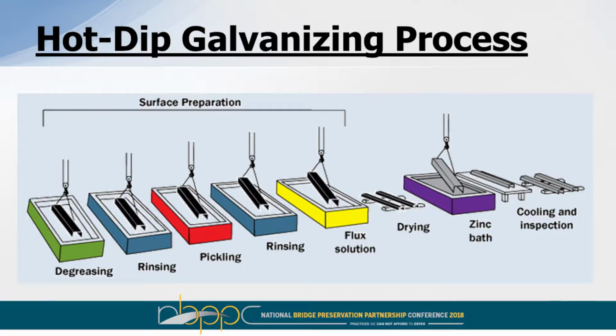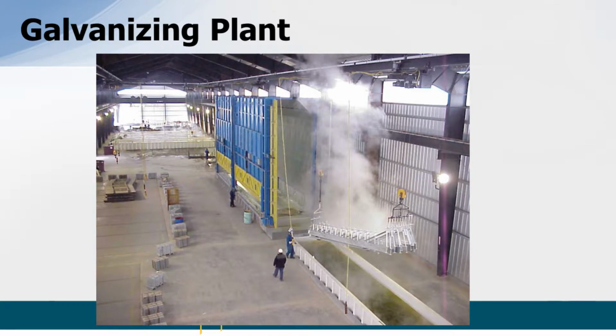It then goes into the bath where it is dipped and reaches 830 degrees, and I'll explain a little bit more of the specifics here in a second. But it reaches the temperature, it's galvanized, it comes out, it has to cool to the touch. Sometimes some galvanizers will quench or passivate the steel. Otherwise, we just let it air cool. And then it's inspected, cleaned, and then ready for shipment. Basically, it's got to be cool enough so you can put it on a truck so it doesn't burn the truck deck.